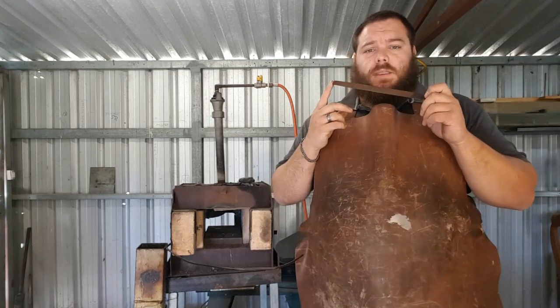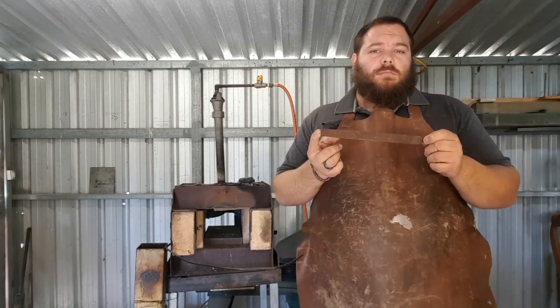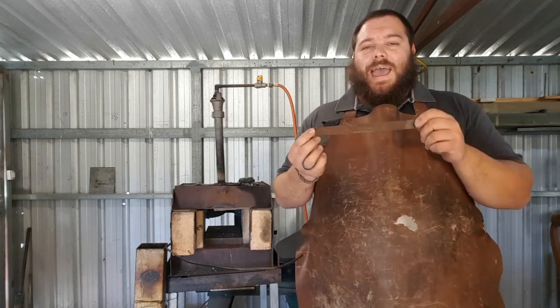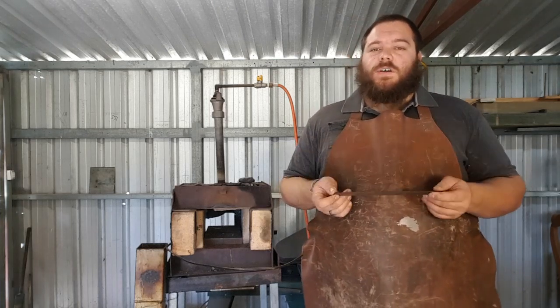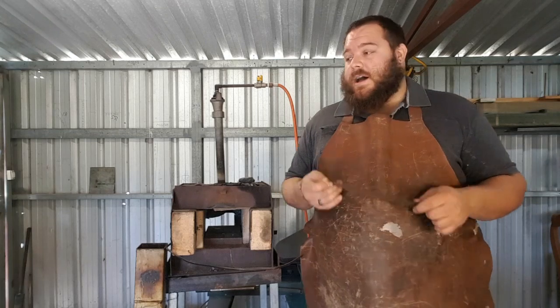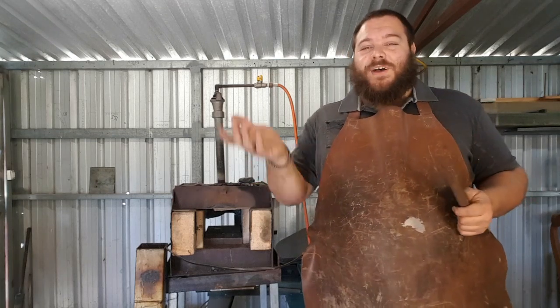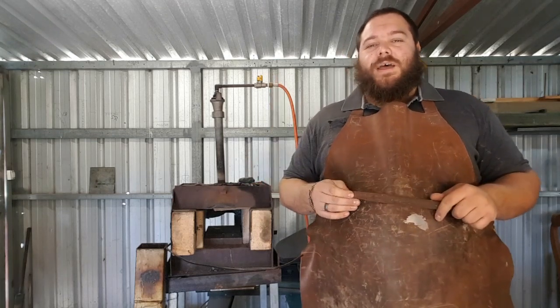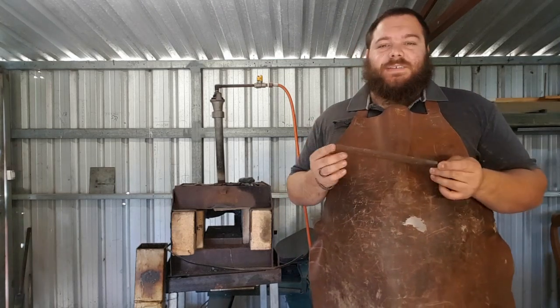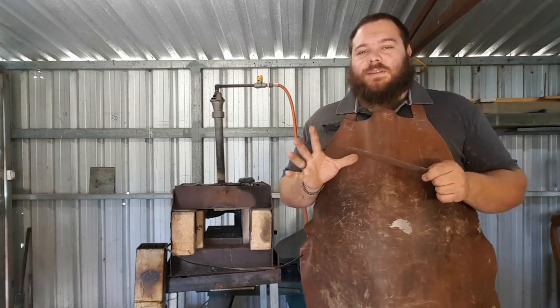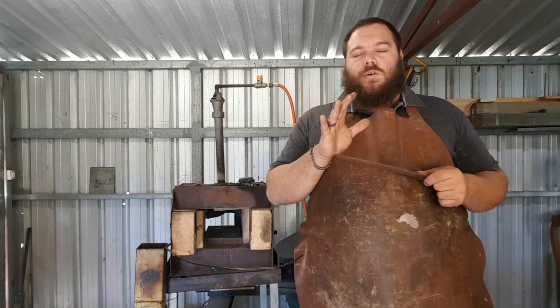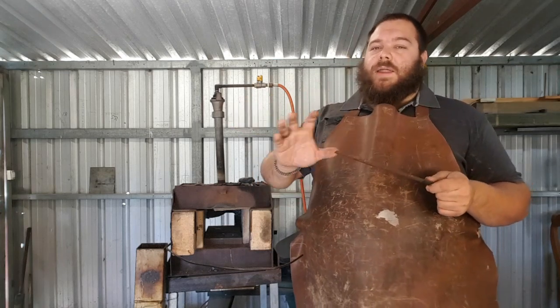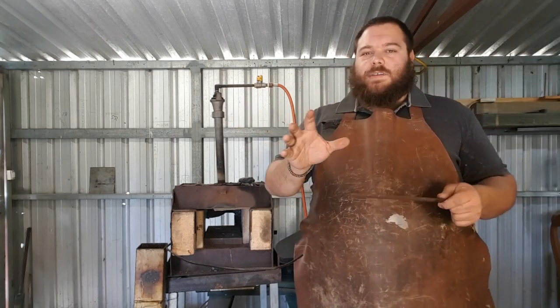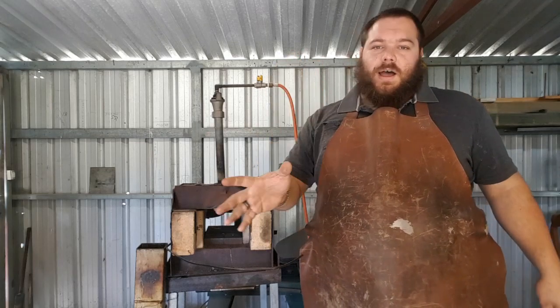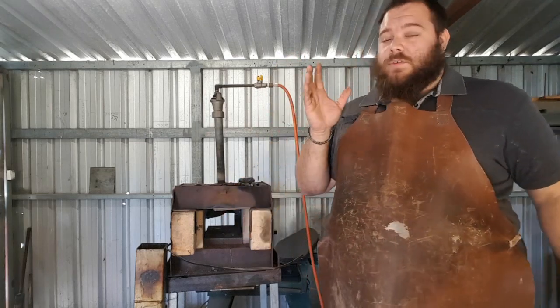So, we know that we need to get it up to 820 degrees Celsius, but how can we tell? The first way we can tell is by using a magnet. I don't actually have my magnet in my shop. I left it at the workshop that I teach at. But basically, once you get to the point where the magnet will not stick, you then heat it just beyond that, watching the color, and get yourself a good heat treating temperature. It's not the most reliable method, but it is a method that you can use.